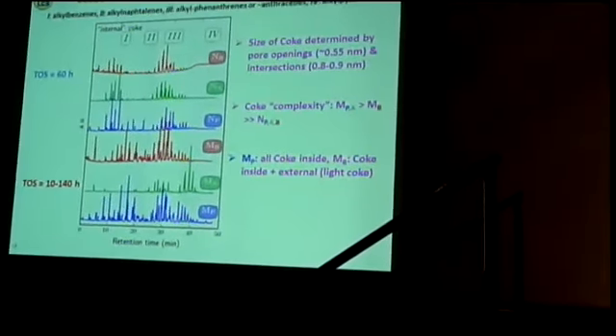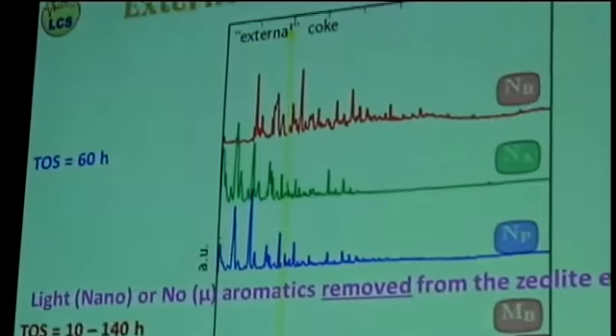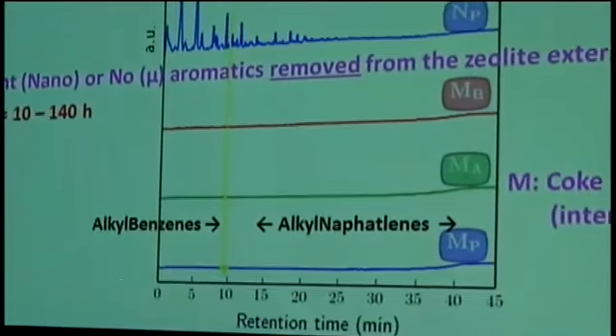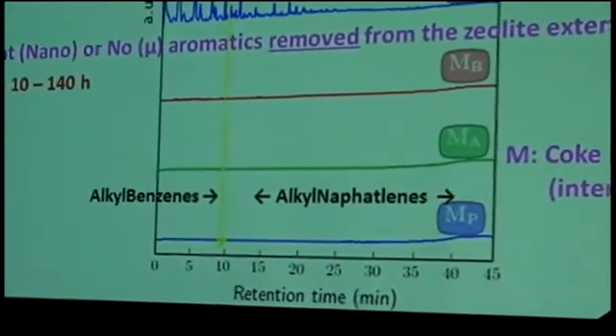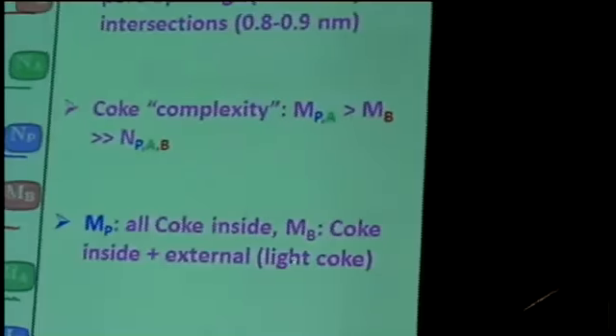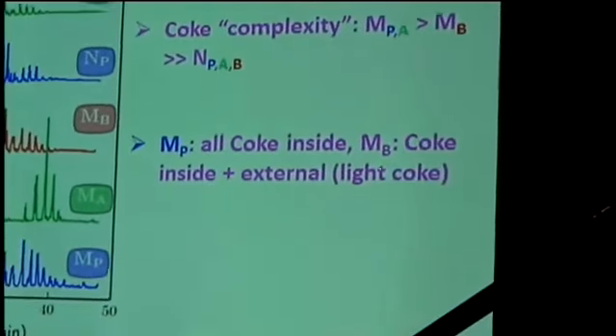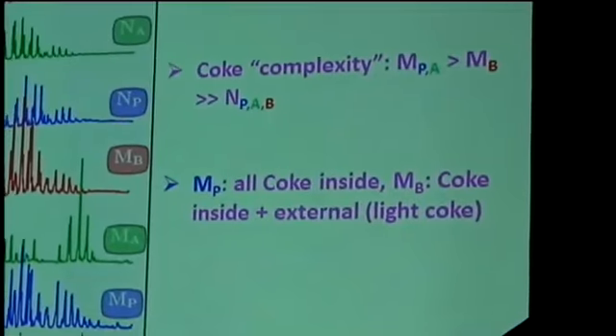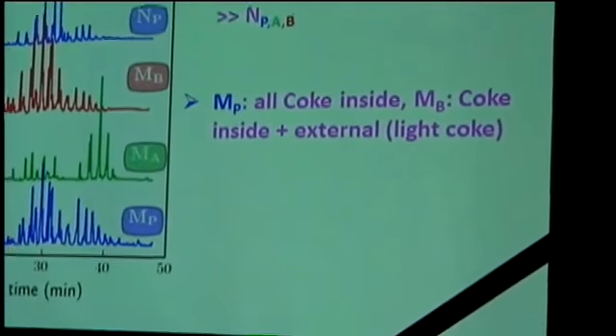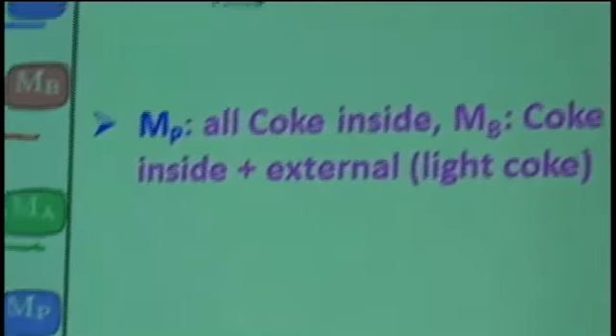And in NP, if we go back here, we don't see any coke on the external surface of the material, okay? And this coke is internal, so you have some light coke that was still trapped inside, and then you have the very heavy coke that is deep inside the material.